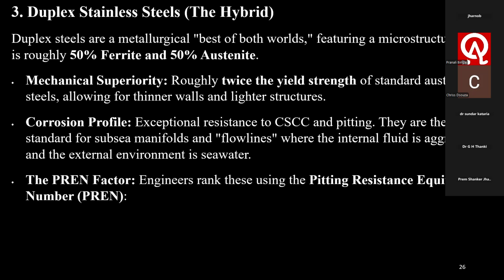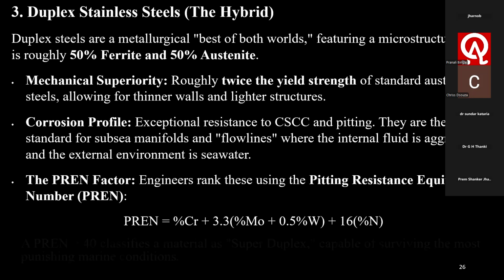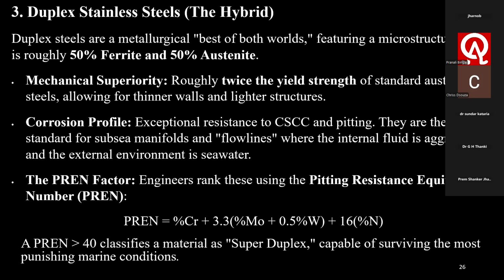Engineers rank these using the pitting resistance equivalent, PREN. This is what you call pitting resistance equivalent: percentage chromium plus 3.3 times the percentage of molybdenum and tungsten, plus 16 times the percentage of nitrogen. If you calculate this, a PREN number comes out, let's say 30, 40, 45 like that. We'll see in the following lecture. A PREN of more than 40 classifies a material as super duplex, capable of surviving the most punishing marine conditions.